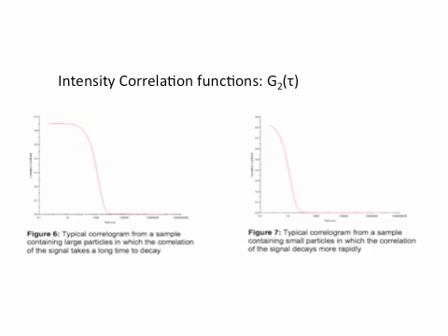Now, obviously, you can also see here in this particular case if you have a bit of a mess in there. So if some of the particles would be coagulated, so you have larger clumps in it, then you will have two different time intervals. You see small particles coming down first, and you see a plateau level, and then the other particles drop down later. And then with DLS, you're in big trouble if that would happen.